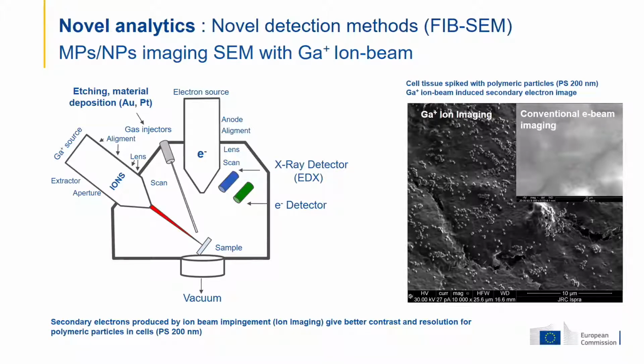We found that using this type of system, imaging with the gallium source results in interaction with plastics, giving a greatly enhanced contrast in the electron images. As you can see by comparing the insert, which is normal SEM imaging, with the larger image obtained with gallium, it clearly shows the presence of a spike of polystyrene nanoparticles placed on this material, which was cellular tissue extracted from muscles.